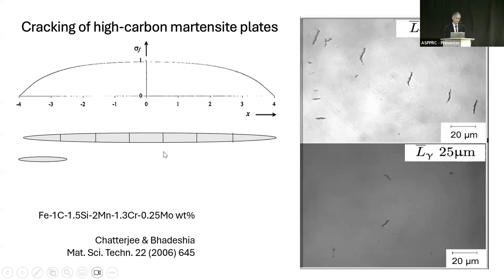So if you make your austenite grain size smaller than the distance between the cracks, then the cracking problem should disappear. Now, how do we make the austenite grain size so small? I want it to be 0.4 of a micrometer. How do we do that?